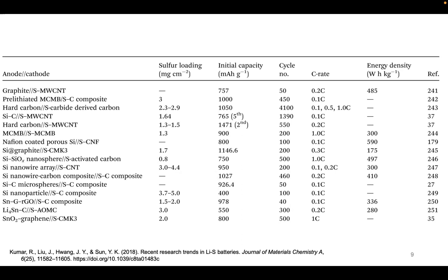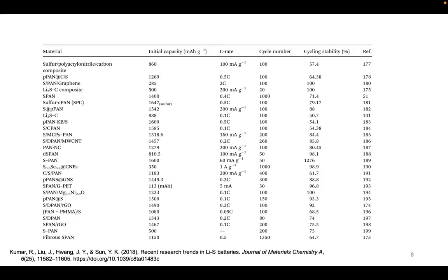Oh, yes. So are these capacities for the sulfur mass, not the total mass? Yes. And very emphatic, yes. And that is because what you'll see is if you have a lot of carbon, then you can really improve the kinetics, right, by increasing the conductivity. But what's going to happen in the long run is the SEI on the carbon is also going to contribute to some deleterious side reaction. So that's something to take into account.